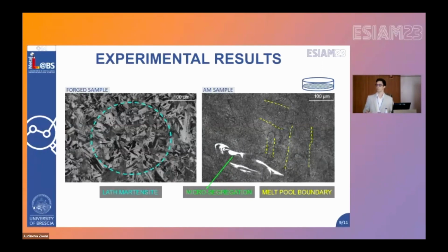And what could be an actual defect are these microsegregations of alloying elements that from previous studies we know to generate austenite at room temperature, that of course is way softer than the martensite.